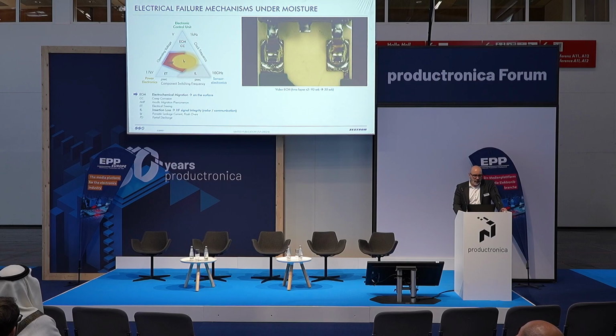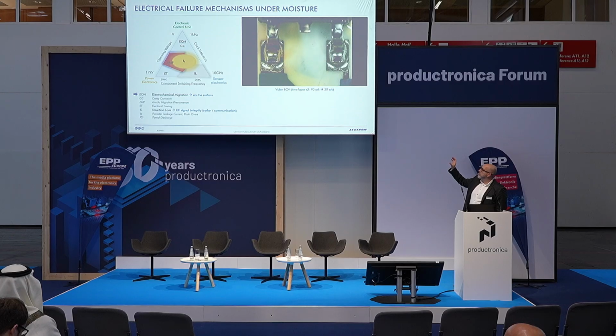So if we go back to electrochemical migration, what does it mean? Here you see a discrete power MOSFET under a test liquid. This is water with some indicator for the pH value. The video you will see is only sped up by a factor of 3, so what you see now is happening in roughly 1.5 minutes. You see a small voltage between the terminals under humidity, and you see electrochemical migration from the cathode to the anode, this kind of tree growth.